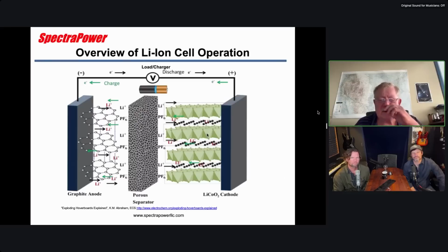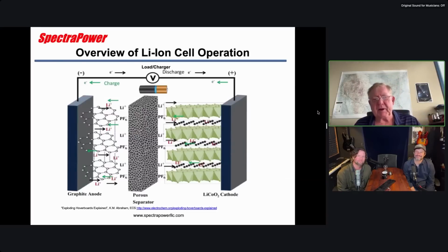When you build a lithium-ion cell, you build it in a discharged state. Over here this is lithium cobalt dioxide, which is very common in portable devices like cell phones because it has the best volumetric energy density and very good gravimetric energy density. But it has a complex structure, and you build the cell with lithium cobalt dioxide, so the lithium is in the cathode. Just think of cathode as positive and anode as negative, by the way, on a cell. Out of habit I'll be referring to them as cathode and anode, but people think of it as positive and negative.